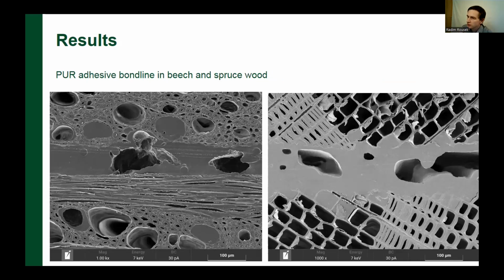Another example of electron microscopy, this is beech wood on the left side and spruce wood on the right side. And there is a layer of polyurethane glue. You can see the penetration of glue to the wood structure. In case of beech, which is more permeable, you can see that the penetration is much better than in case of spruce on the right side. You can see the penetration is just maybe two cells. Even if there are some bubbles or cavities in the bond line, it's still very well bonded together.